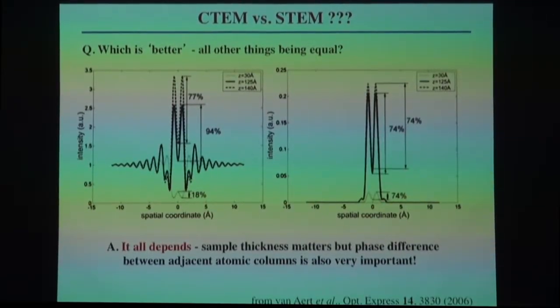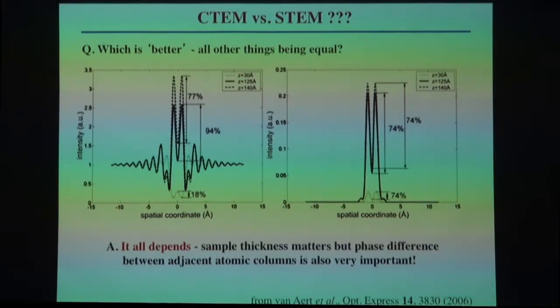Okay. It turns out that it depends, very nicely shown by Sandra Van Aert several years ago. Which is better, all other things being equal? The answer is it all depends. It all depends because the sample thickness matters, and the phase difference between adjacent columns will depend on the thickness. So there's a comparison here of STEM and TEM. And depending on the circumstances, TEM will sometimes give you better resolution than STEM, and other times STEM will give you better resolution than TEM. So it all depends. You were quite right to sit on the fence and not make a commitment.